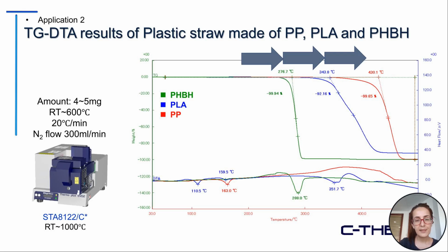As you can see, the green curve is related to the PHBH, the blue curve is related to the PLA, and the red curve is related to the PP. The thermal decomposition temperature of the PHBH is much lower than the PLA, followed by the PP. In the DTA, we can see a couple of transition temperatures, which are all endothermic peaks, but we couldn't tell whether they are related to melting or another transition. Therefore, we did another experiment.